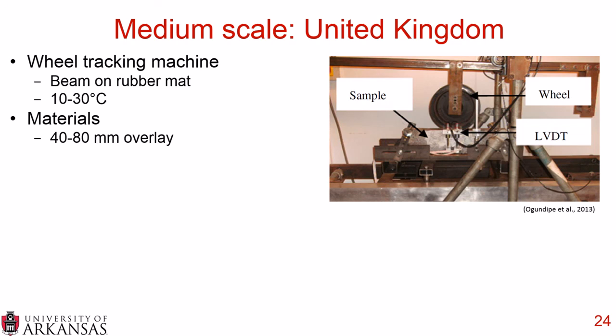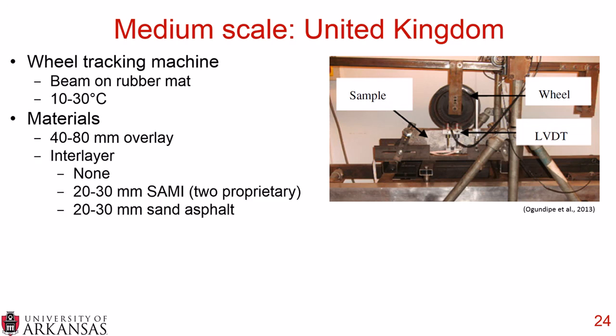The 80 millimeter overlay was the control, so there was no interlayer. So they used 3 different configurations of interlayers. No interlayer, which was the 80 millimeters. Then they used 20 to 30 millimeters of SAMI, and they used 2 proprietary mixtures, and they compared that to 20 to 30 millimeters of sand asphalt.